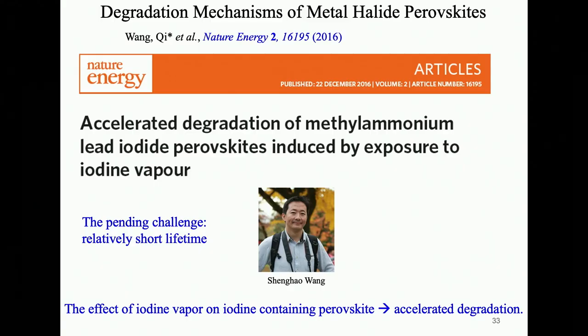As I mentioned in one of the previous slides, one of the pending challenges for perovskite solar cells is their relatively short lifetime. To get a better understanding of this issue, we studied the effect of iodine vapor on the iodine-containing perovskite and observed accelerated degradation. This study was performed by Shenghao Wang. In the next couple of slides, I would like to use a cartoon animation to illustrate such effects.